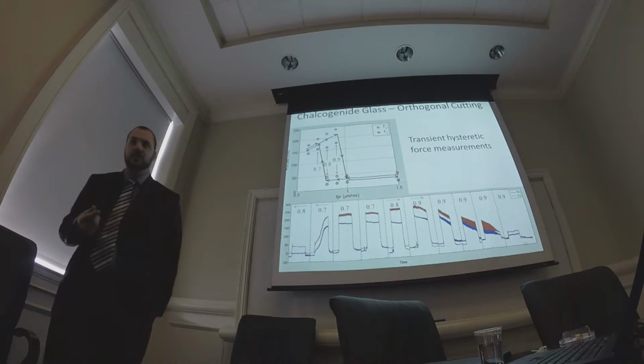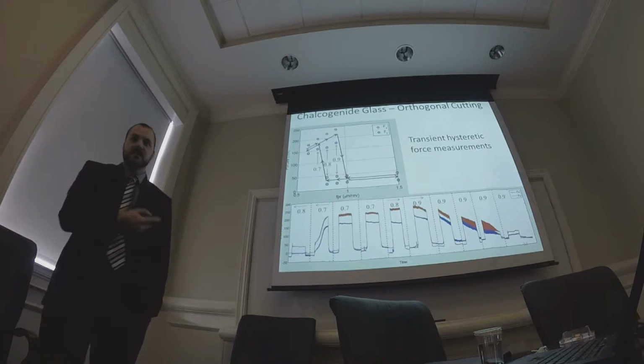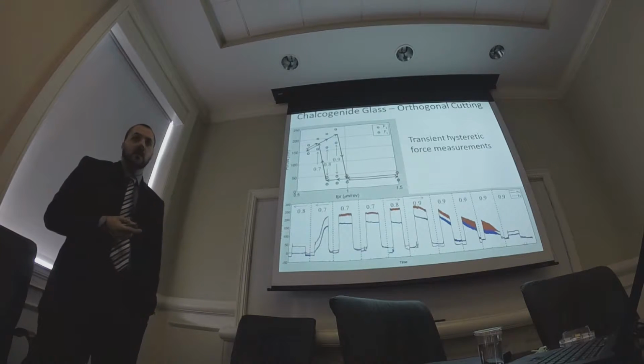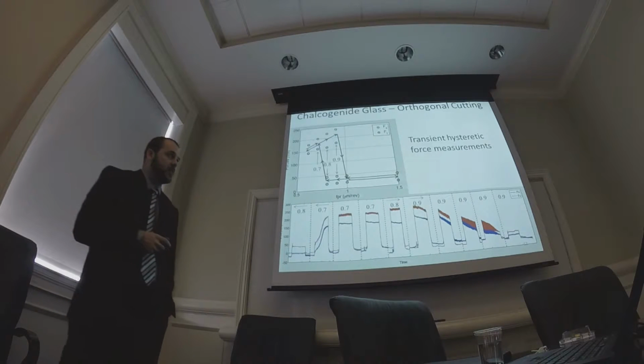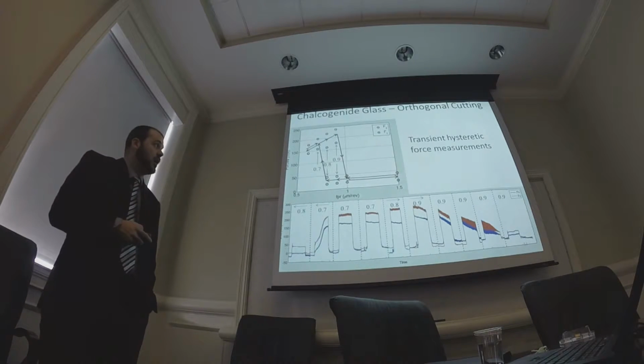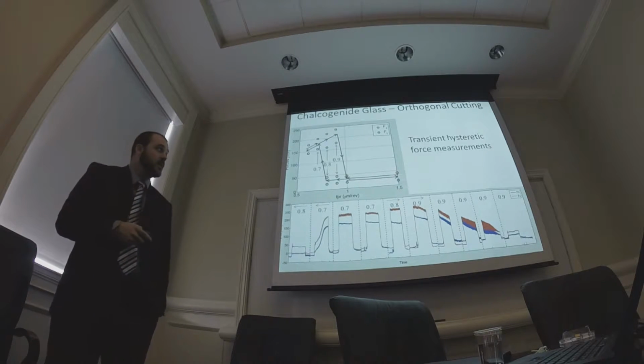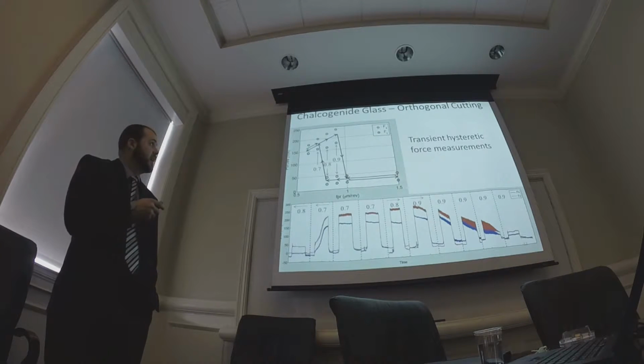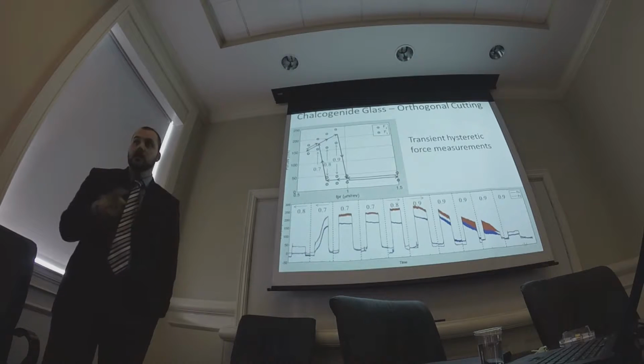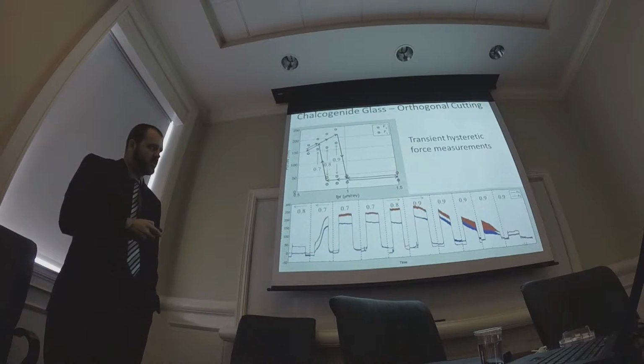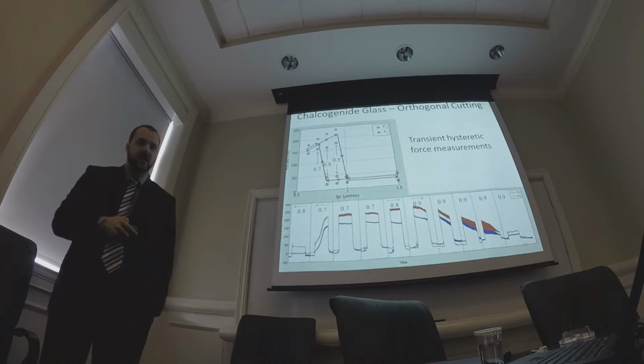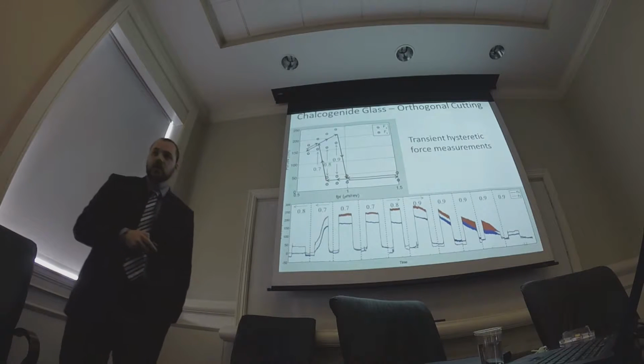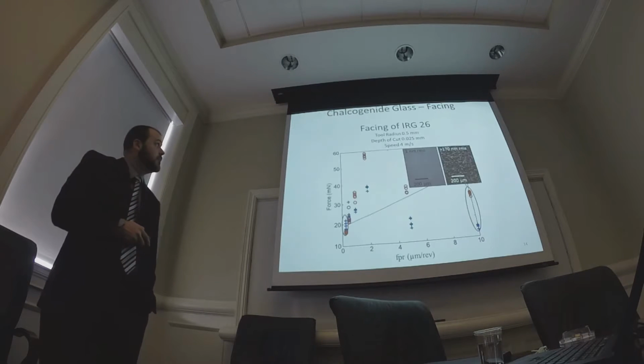There's also some concerns that the IRG-26 isn't completely homogeneous, so there may be some material dependency as well throughout the sample. But lots and lots of tests were repeated, and this 900 nanometers to a micron transition was seen throughout all of our testing. This was 320 revolutions of data just to get through to a steady state.